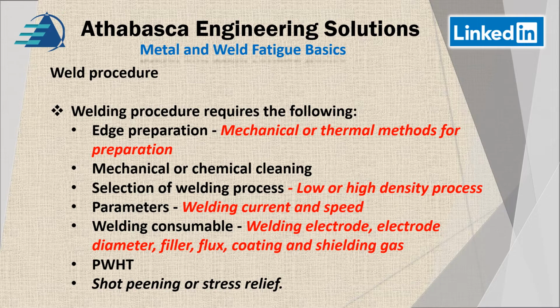That's looking at putting it in the oven to reduce the stress in the welds, which is when I looked at the API 579 in more detail, there are sections on that where you can actually do a calculation. You can see the effects of stress relief, and perhaps I'll do that in a future video, and it's quite remarkable. One calculation I did basically demonstrated that the stress could be dropped by like 90% by doing stress relief, in terms of reducing the internal stresses in the part, which is one of the key elements for improving the fatigue life of a part.